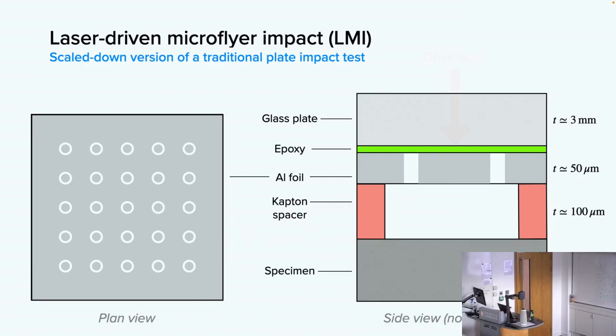And the way in which I'm going to do the experiment now is I'm going to come in with a drive laser. That drive laser is going to cause vaporization of the epoxy. The expansion of that vapor now is going to detach the aluminum foil disc and is going to launch it toward my target, again at a velocity of 1 to 2 kilometers per second. Once that little microflyer hits the target, now my waves propagate in the way that I just showed.